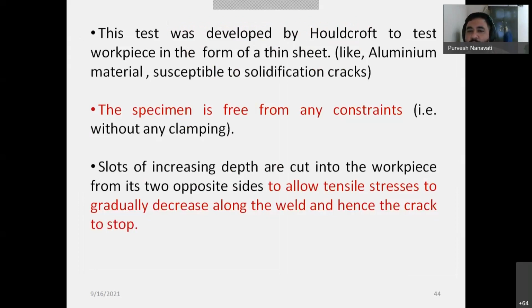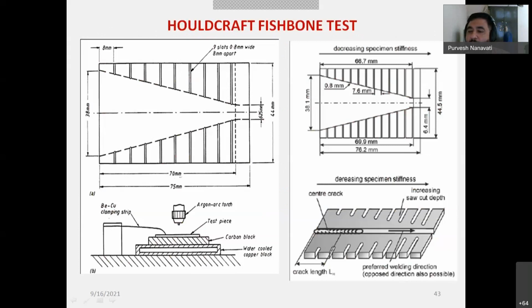Slots of increasing depth are cut into the workpiece from its two opposite sides to allow the tensile stresses to gradually decrease along the weld and hence the crack to stop. Now, there will be tensile stresses developed. What will happen? Because you have no space available to distribute your stress, right? As you move along, these tensile stresses will be developed because the moving heat source or the weld pool will try to contract, and you have a resistance to contraction because of the less bulk metal volume available surrounding it. So what will happen as a result? You have decreasing tensile residual stresses, right?